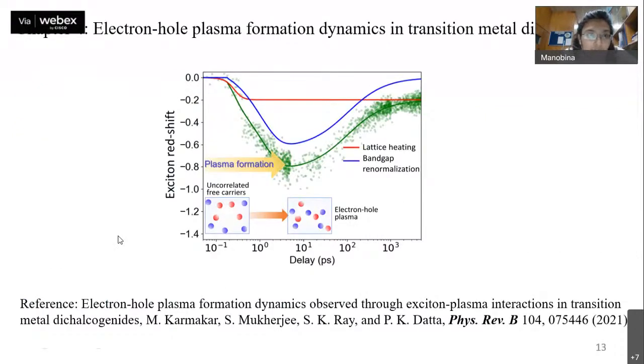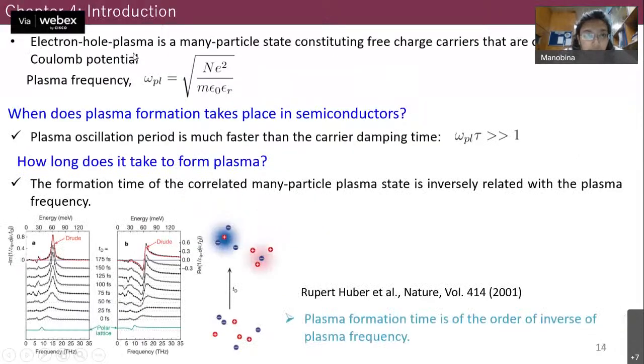So next I move on to the next chapter, electron hole plasma formation dynamics in transition metal dichalcogenides. So electron hole plasma, as we know, is a many particle state constituting of free charge carriers that are correlated via Coulomb potential. Plasma frequency is related with the square root of n, which is the number of charge carriers present. And the main criterion for plasma formation is this: omega_p times tau is much greater than 1, where tau is some time of carrier scattering or other damping time.